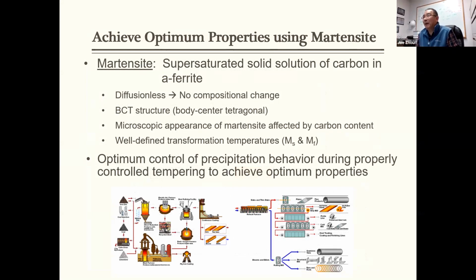People use martensite structures to achieve the optimum properties, because martensite is a supersaturated solid solution. It's not only saturated with carbon, it's also saturated with all other alloy elements. So this gives the metallurgist the opportunity, through tempering, to control how the precipitates come out to achieve the best mechanical property. In other words, the 91 gets these beautiful mechanical properties by generating a unique microstructure through tightly controlled composition and tightly controlled heat treatment.